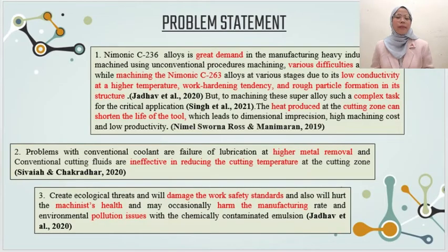The problem statement in this project: first, Nimonic C-263 alloy is in great demand in heavy industry, but very great difficulty is observed while machining this alloy at various stages due to its low conductivity at higher temperature, work hardening tendency, and rough particle formation in its structure. Due to high temperature during machining, the heat produced at the cutting zone can shorten the life of